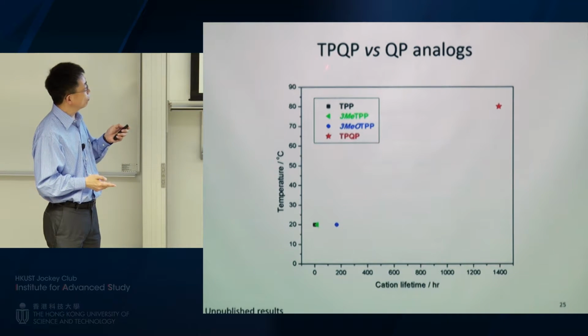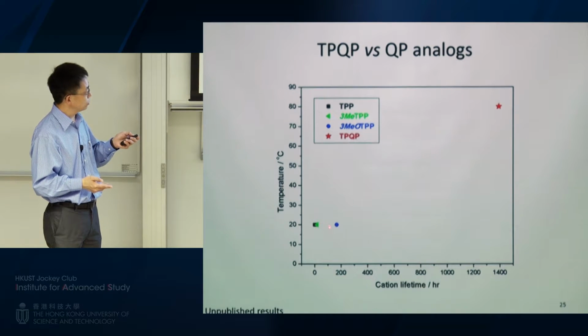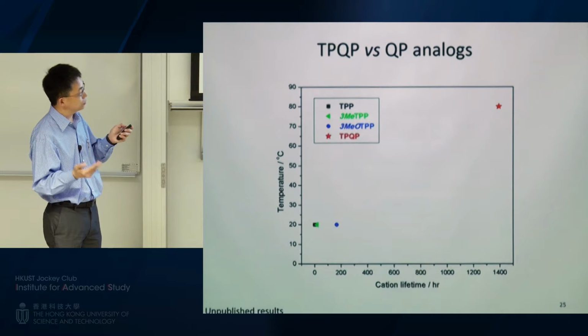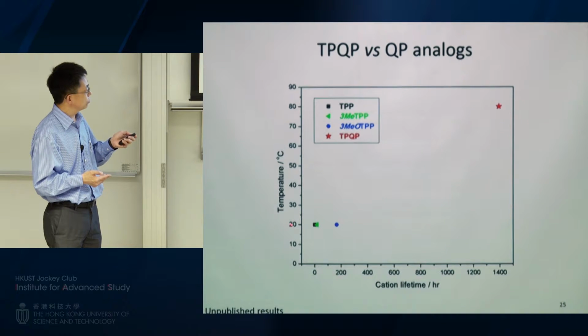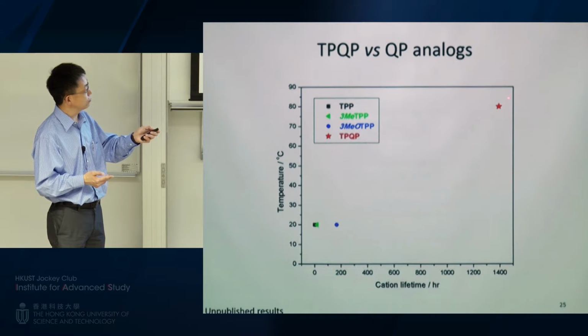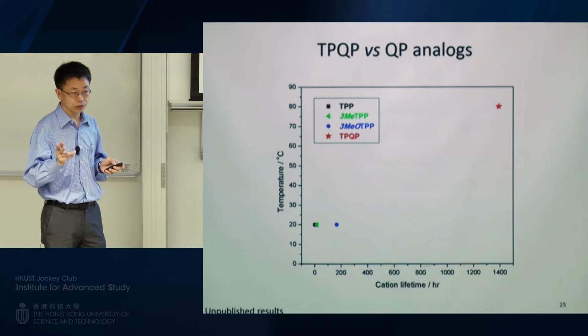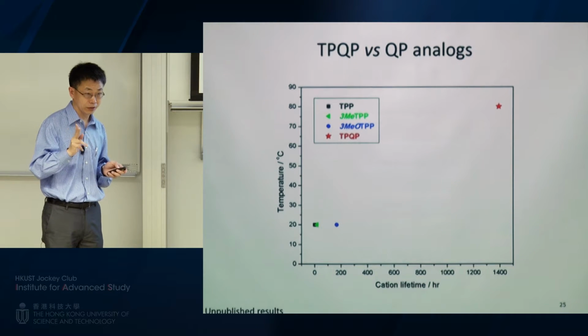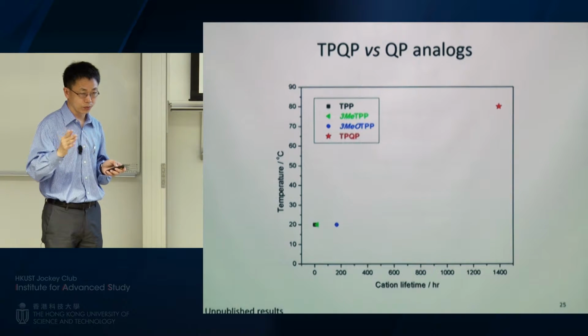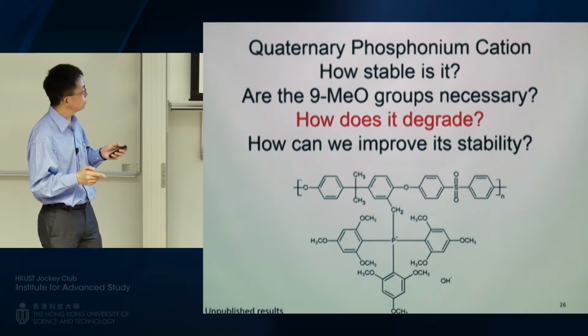So if you put all of them together, these are the three: single substitution or zero substitution, and this is our 9-methoxy substitution. You can see this is the lifetime, and this is the temperature. Usually higher temperature means lower lifetime. So this, even at a lower temperature, is still much less stable in terms of time than this one at a much higher temperature. So that shows you 9 methoxy groups are necessary. And once again, we have a lot more data than this, but I think you get the point.